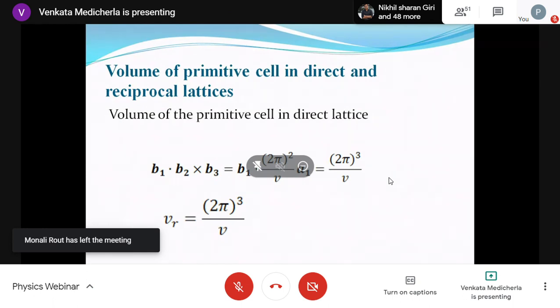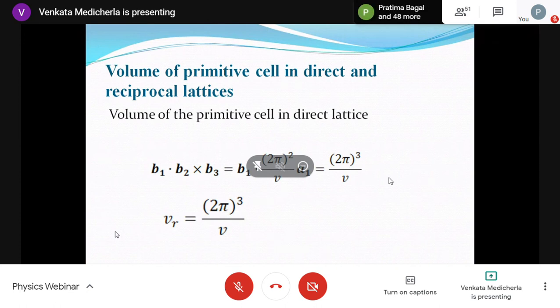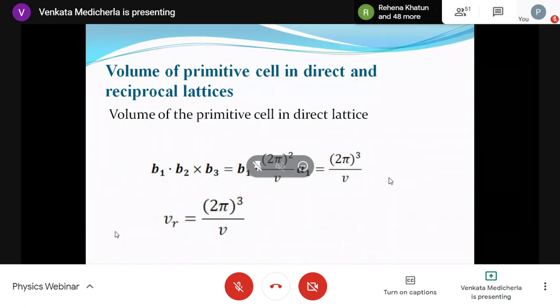There are things easier in the Bravais lattice, but many things that are very difficult in direct space are simpler in reciprocal space. For example, band structure of materials is always plotted in k-space, which is reciprocal space — E vs k, where kx, ky, kz are reciprocal lattice coordinates. Whole sections of solid state physics are essentially entirely in k-space.